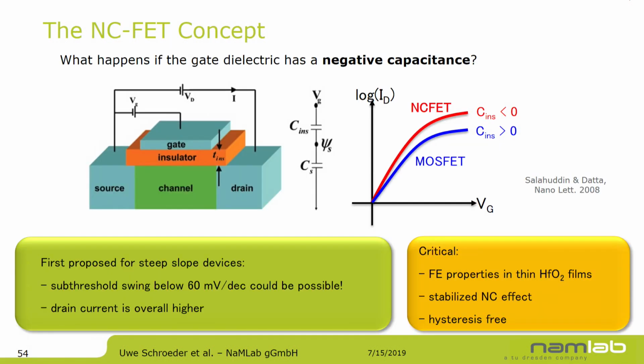And the thing is, if you now look at device conferences, there will be a lot of sessions on these negative capacitance effects. The critical thing, coming from the material point of view, is really looking at whether these 2 nanometer films they're putting into the device structures are really ferroelectric. With your knowledge, it's typically easy to see. And the other thing, from the device point of view, is that you need a hysteresis-free switching behavior, because if you had a hysteresis, you wouldn't be able to use your transistor in the normal operation mode.